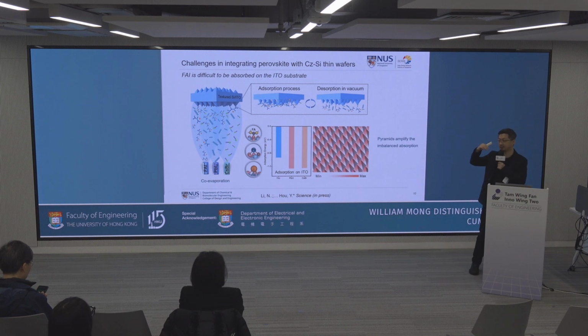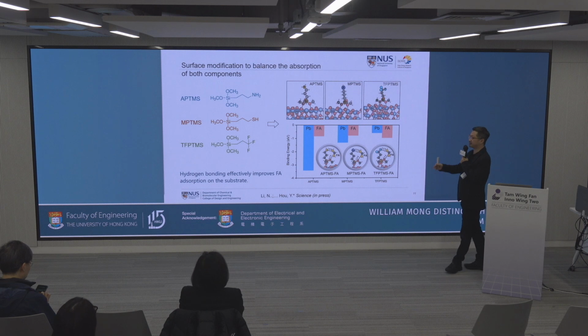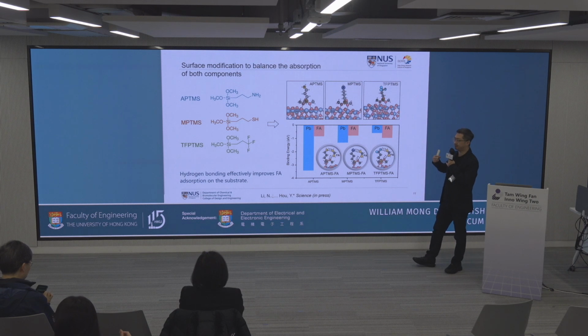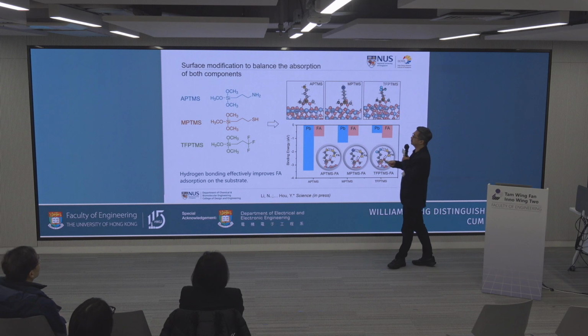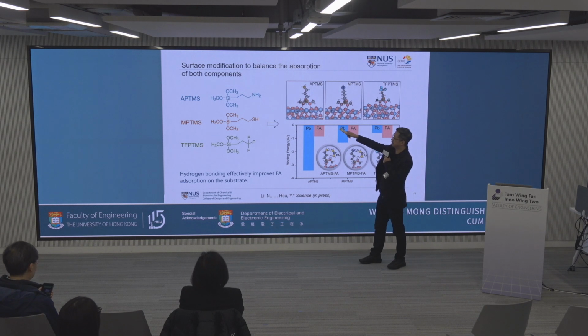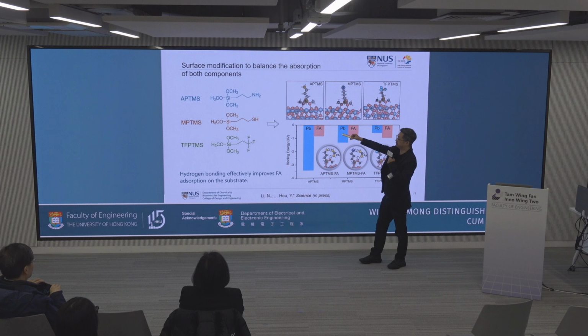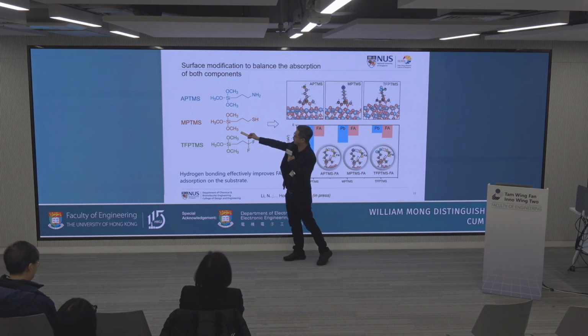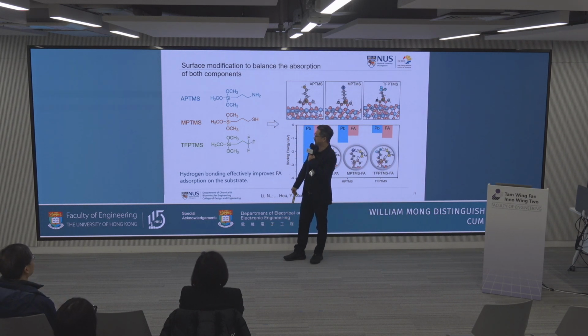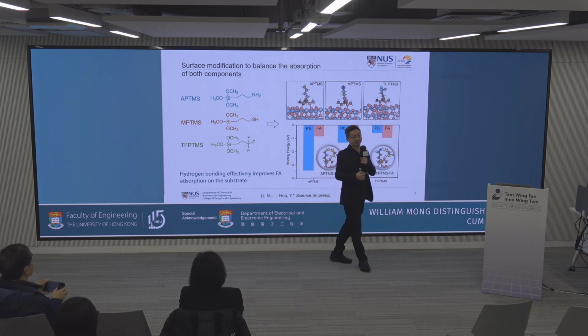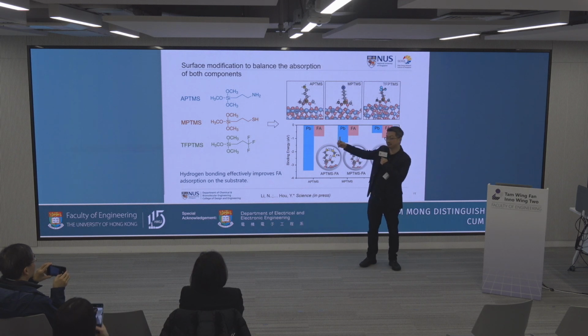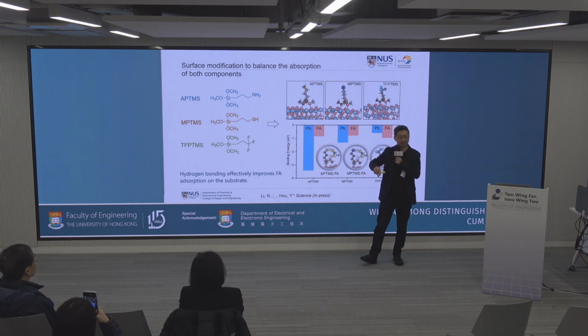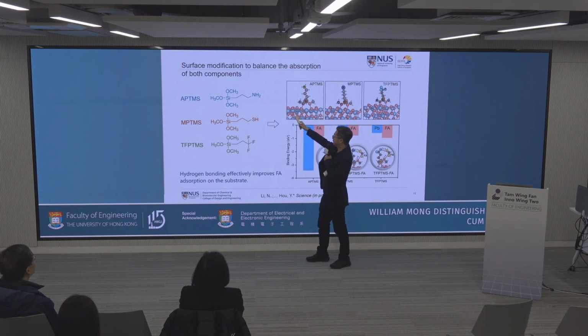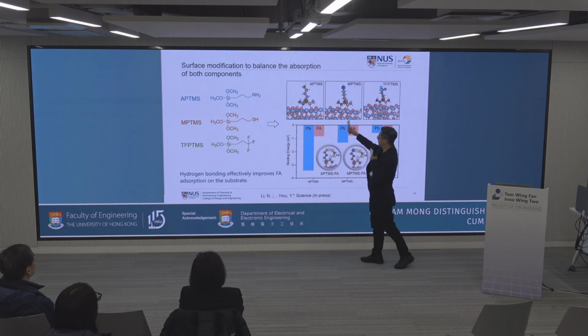Because this pyramid has a peak, and this base position is also very different. So we want to solve this imbalanced absorption of the perovskite vapor on the substrate. And what we did is we modified the surface with this silane group, these small molecules. And this is a typical silane group, and this part can attach to this ITO and the metal oxide. And then you have the functional group. So it's very similar to the self-assembled monolayer, but the anchoring group is now switched to the silane group. Previously we used phosphonic acid, but the functional group just helps us to adjust this imbalance of the absorption.